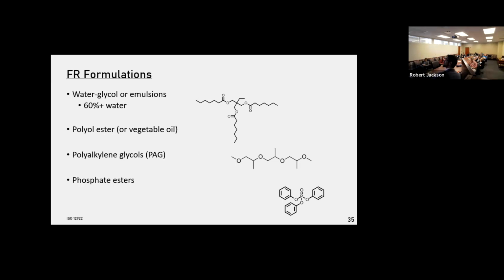So to show you some chemical structures, most popular is water glycol. If you use 60% water, you might automatically pass, but there's a lot of issues with having water. You've got to worry about the effects of microbes and things. That's become a big workplace issue, the people being exposed to microbes growing in the water. You can use polyol esters, even vegetable oils, polyalkylene glycols, or as I said, phosphate esters. These all have better cohesion, lower volatility, higher fire points, and they have tended to be safer.